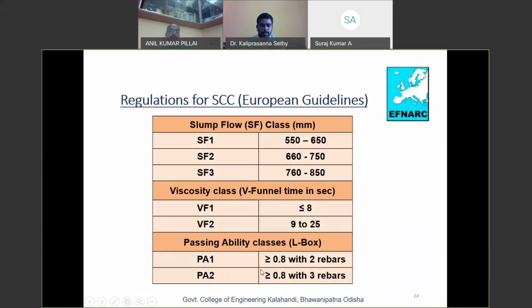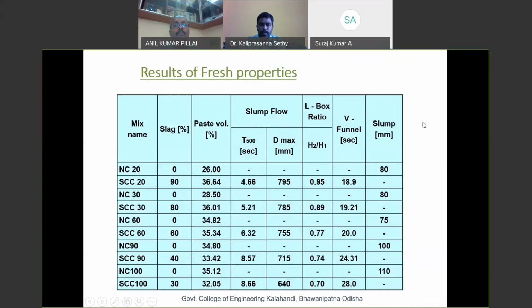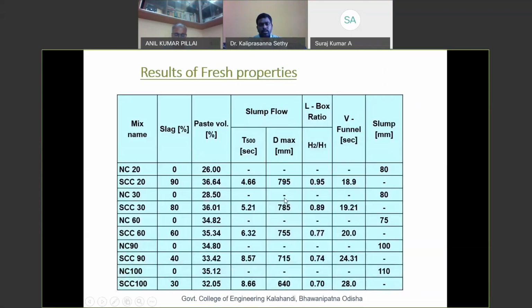You can see all are in this range, and since we are using a 3-bar L-box, this is categorized as PA2. This is the value for the V-funnel flow duration in seconds: 18.9, 19.21, 20, 24, 28. From this you can see this is categorized as VF1 and VF2. Once we certify the concrete as self-compacting concrete in the fresh state, we can move towards the mechanical property check.